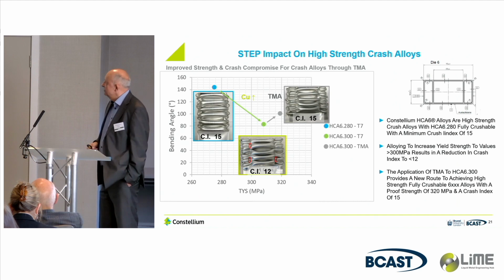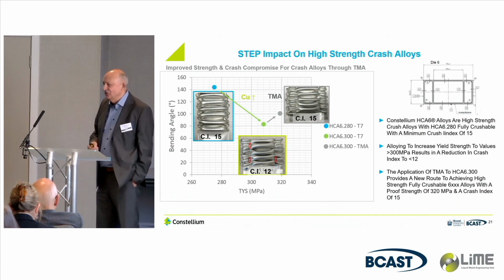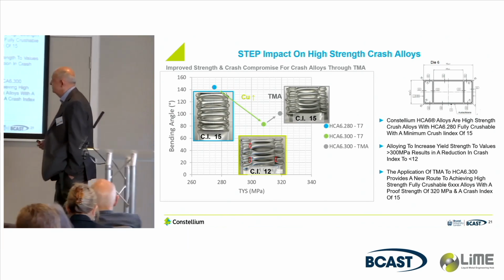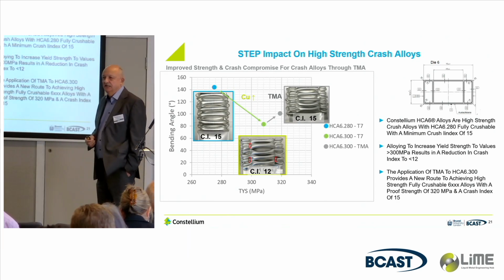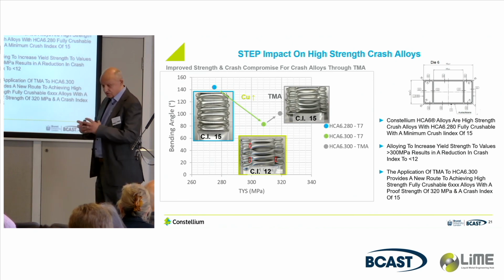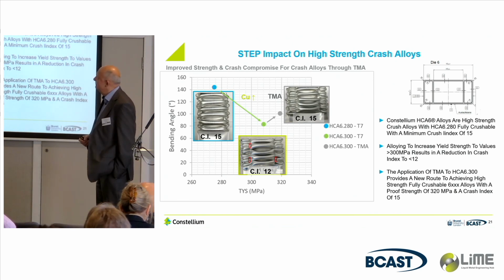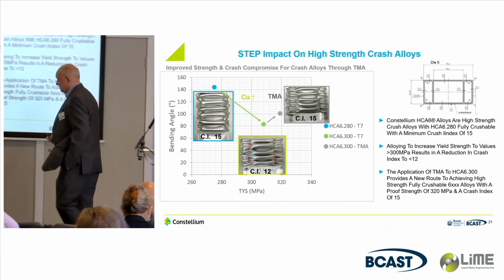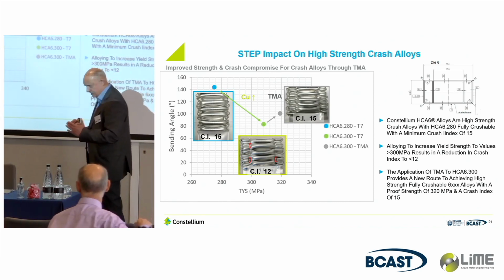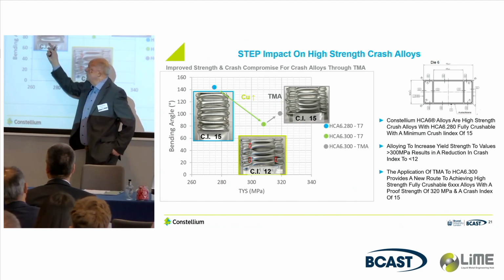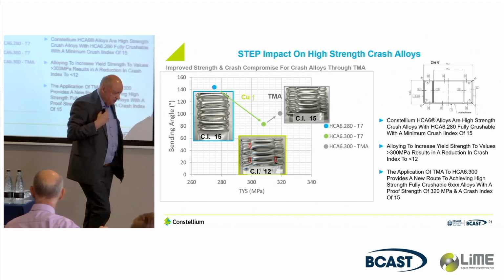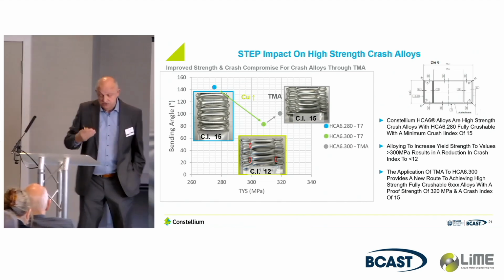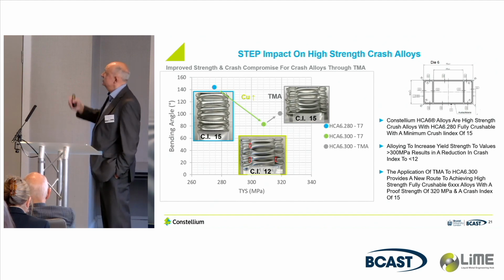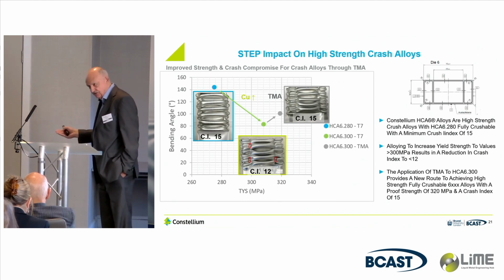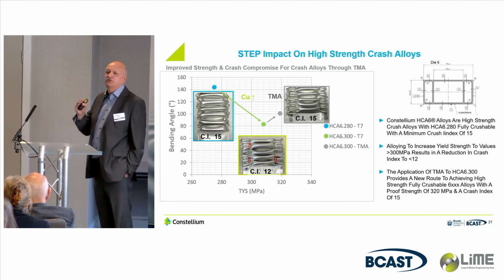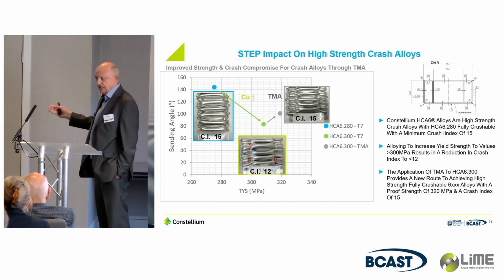One interesting thing that we've also learned, and we haven't got an answer to this, by the way, and which is somewhat counterintuitive, is when we apply levels of cold work, so stretching in this case, to a crush material. So we imagine now in a crush situation, we're crushing that material, so this folds, absorbs the energy. As you increase the composition, as you increase the strength, what tends to happen is the crash index begins to fall, and ultimately, once you get above about 300 megapascals, you start to develop cracks.